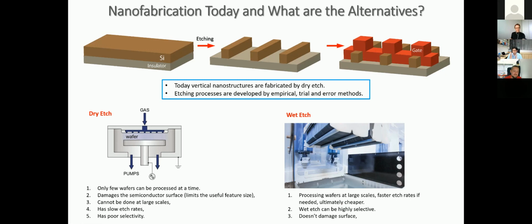So you bombard with these energetic ions that react and then eat away the material, and you end up with the desired structures, and then you do your metallization process, or you deposit whatever you want. Most of the time, this reactive ion etching is called dry reactive ion etching. So it's done inside this plasma chamber. You put your wafer in there, and you have to be able to generate a very uniform plasma and so on.